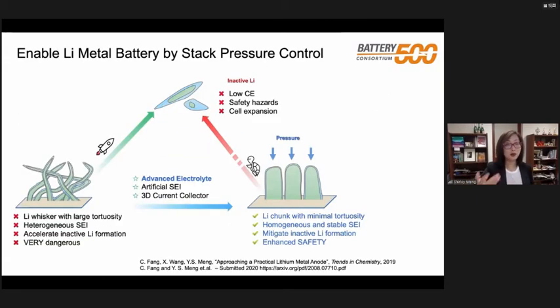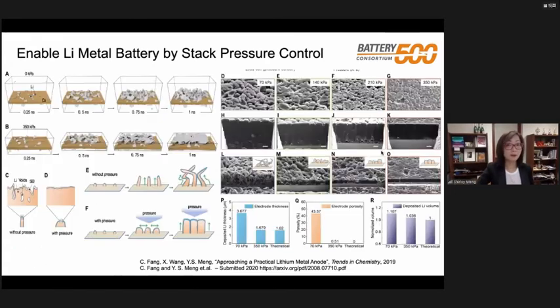One of the most important or successful examples we have shown: we worked a little bit on a 3D current collector. I don't have time to go through it today, but I will show you that with a certain amount of pressure control, we can very successfully deposit. This bar is 2 micron, okay? So we are actually depositing 20 micron of dense lithium and stripping this lithium under a very moderate pressure level.